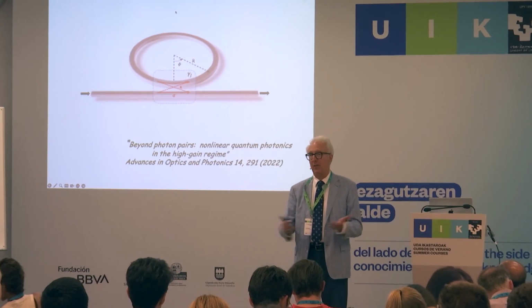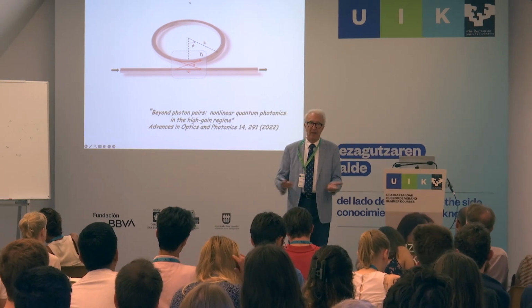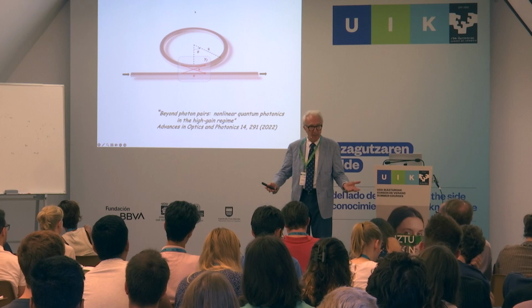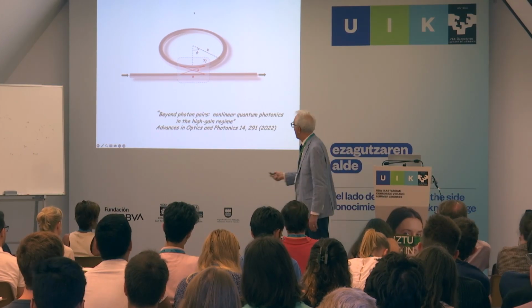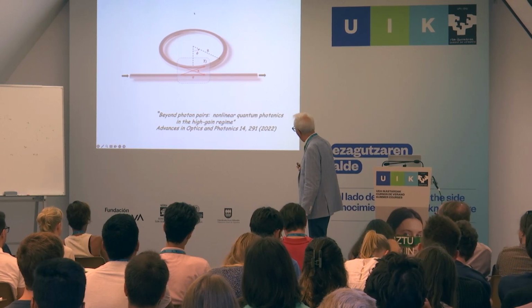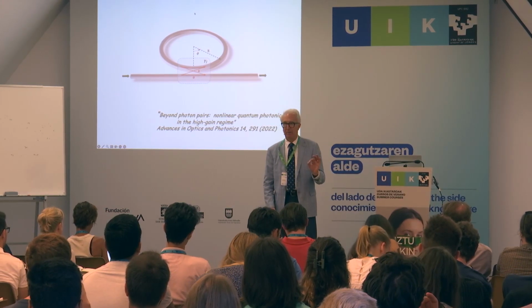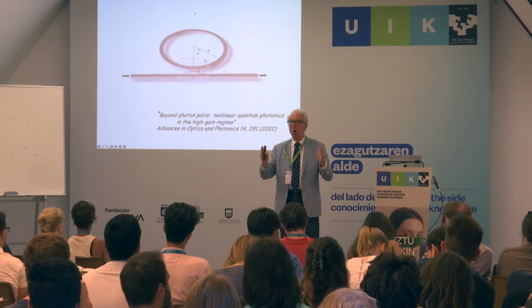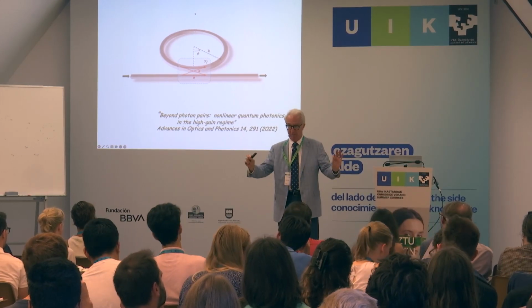So it's a wide bandgap semiconductor, transparent at 1.5 microns, at half that wavelength, and I think even at 4 times that wavelength, okay? And people know how to make structures out of it with incredibly low losses. I'm talking dBs per meter in a nanostructure.